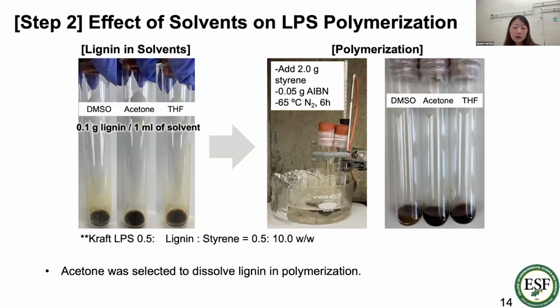And after the polymerization, we considered which solvent could be removed most efficiently from the polystyrene, and we selected acetone for the further study.